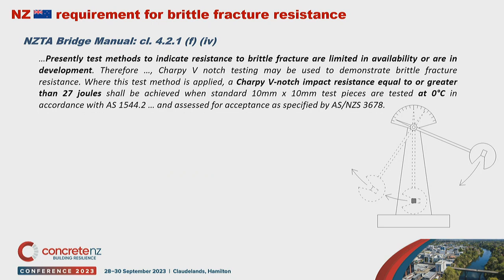So the Charpy V-notch test is generally a 10 by 10 by 55 mm sample that is cut out from the coupler, then it's frozen at 0 degrees and put in the Charpy pendulum, and the energy that is absorbed by the sample gives an indication of how ductile and resilient the material is. If the pendulum swings up high and there is a brittle failure, there is little energy absorbed, so we know that it's not a good material. In this case, 27 joules is the threshold.